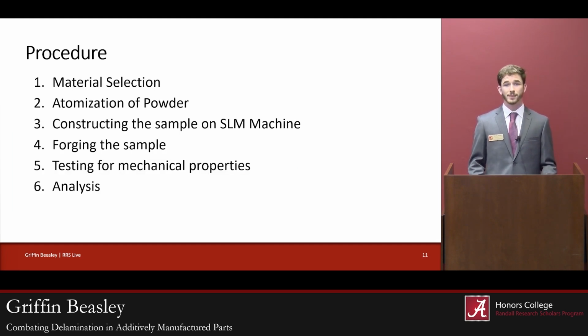Our procedure for these experiments is very efficient and simple, which will allow us to repeat it multiple times very quickly with multiple different alloys. Our first step is to select the alloy that we would like to use. We will then put this alloy through something called atomization. Atomization is the process of melting down a piece of metal and resolidifying it in a powder state. There is an atomizer facility here on campus that we will be able to use for this experiment.